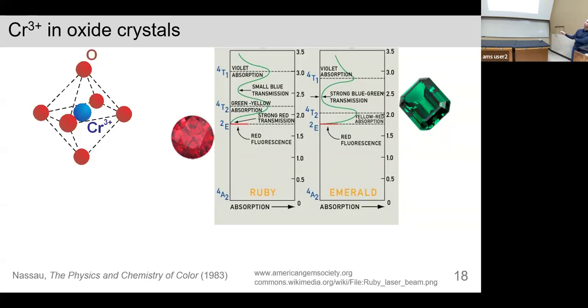And the absorption shown here is in the green curve. It absorbs in the violet and the green yellow. It has strong red transmission, and so it gives it this red color. So these absorption bands are due to exciting an electron from its ground state in the chromium to an excited state. So the d electron going to a higher energy level.